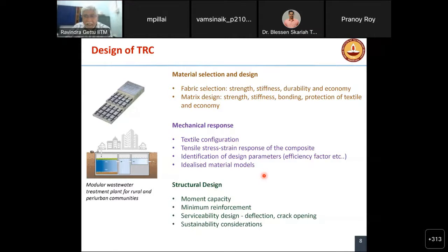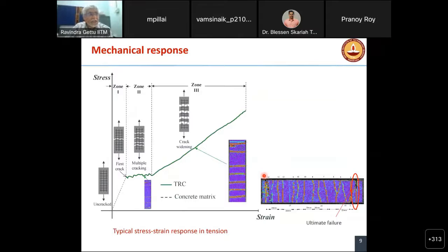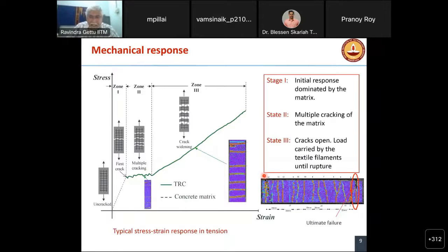Okay. So next, let me look at the mechanical response. This is what happens when you test a panel of textile reinforced concrete. These are images from digital image correlation of one of my students, Ramakrishna, who's just finishing this work, where you see that as the uncracked element is loaded, there is first a crack which is occurring somewhere at a weak section. Then the textile starts to bridge. Once the textile starts to bridge, that section no longer is weak.